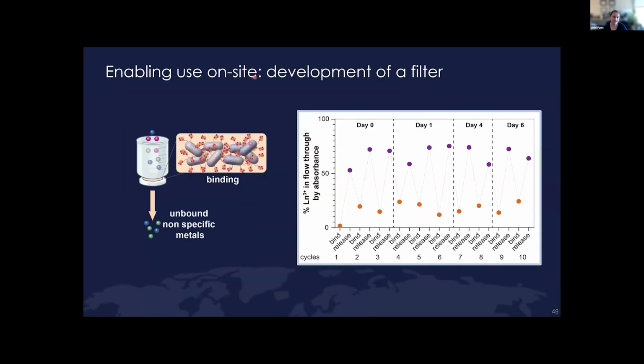And so what we've been able to do initially is just to develop this as a packed bed filter. So if we put these surface displayed protein materials in a filter and flow through our mixture that contains rare earth elements, anything that is not specific for that protein, so things like magnesium, calcium, iron, all flow through, while we get our target lanthanides bound to those materials, which we can then release, as you can see here, with just a lower pH wash. So shown across the course of 10 days, we see this cycling of binding and release. And what this shows us is that we get about an 83% total recovery. And that corresponds to about twice as much recovery as current methods for rare earth separation.